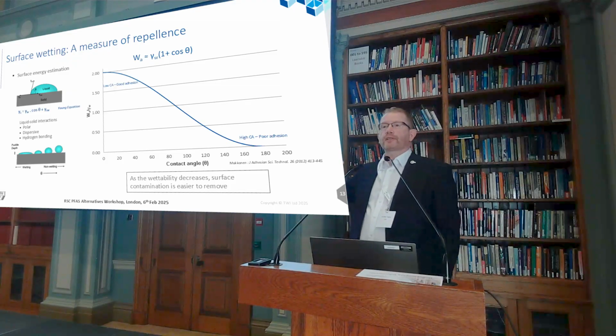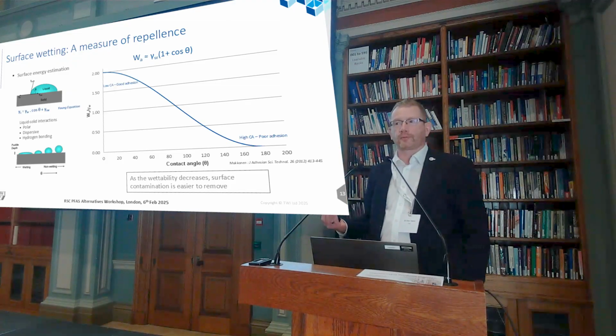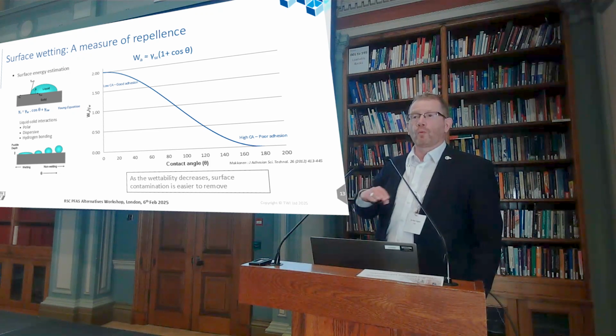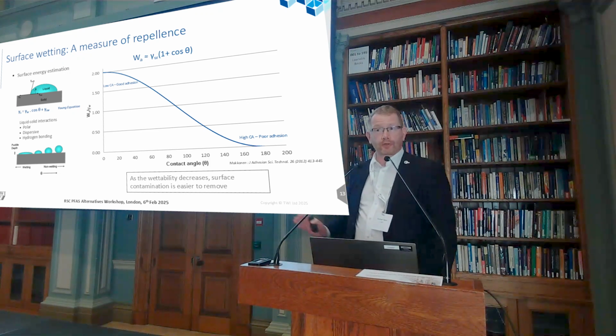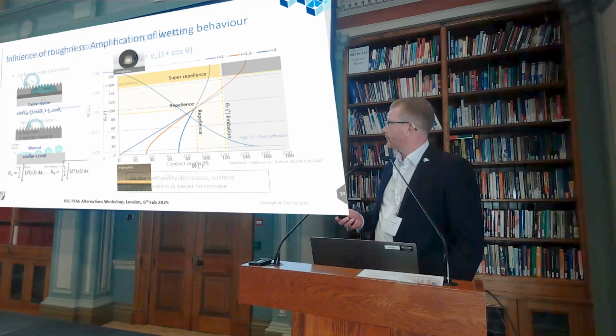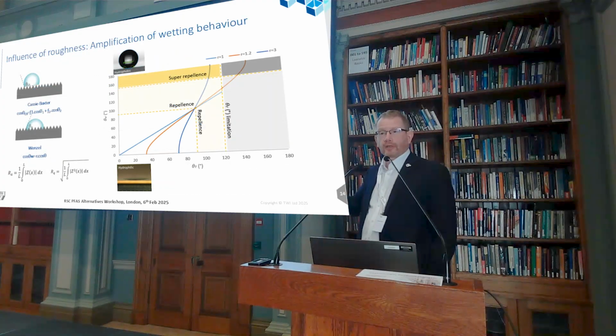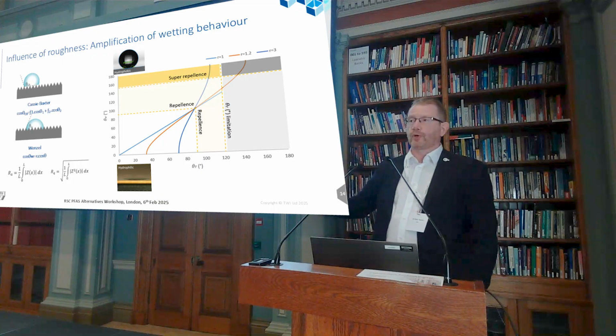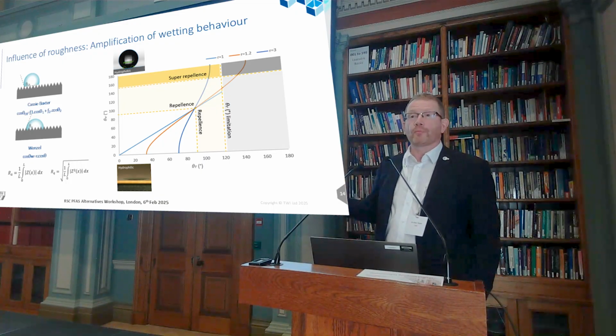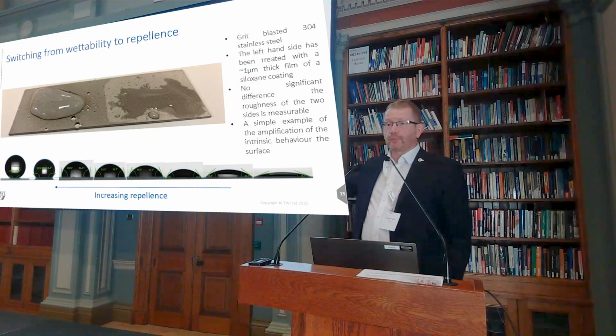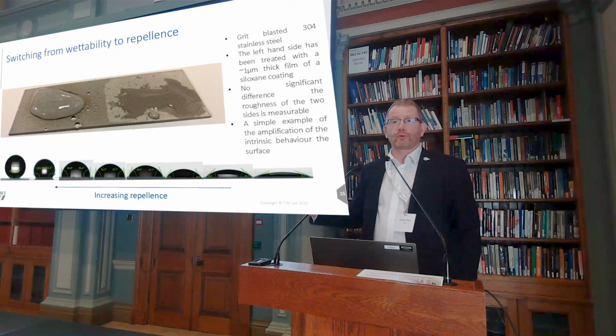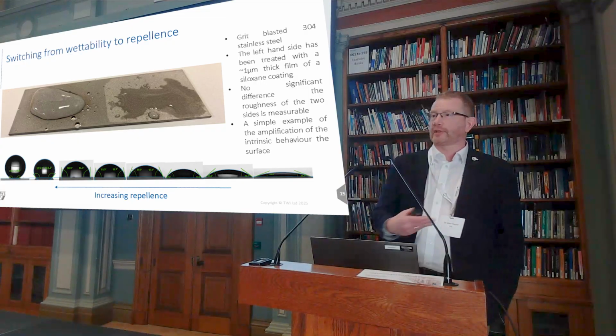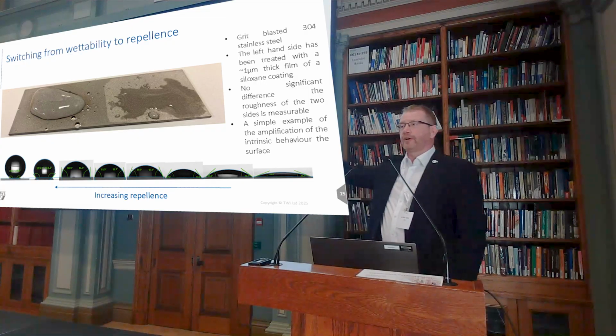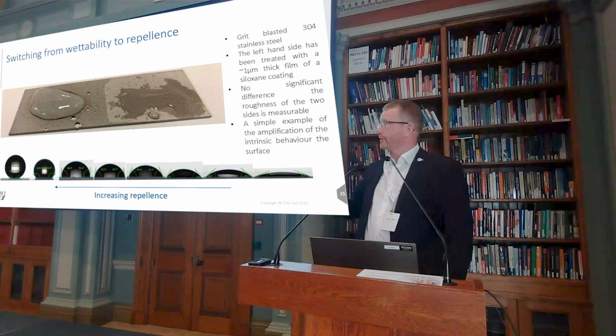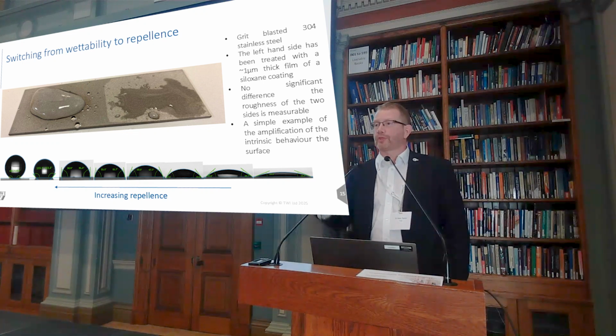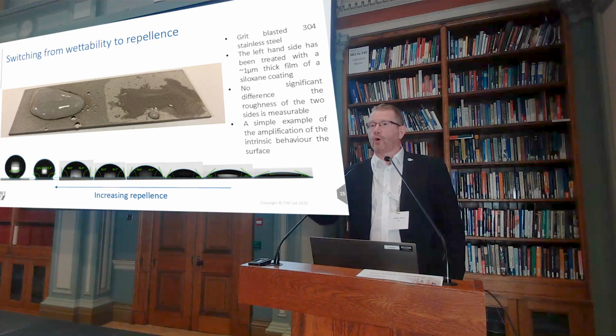So, quick graphs in terms of contact angle, because people always bring that up when you're talking in terms of hydrophobicity. Fluoropolymers, when there's no structure, tap out at about 120 degrees. If you want a higher contact angle than that, you've got to build in some roughness. And again, we've done quite a lot of work on the relationship between topography and chemistry in order to manipulate behaviours and repellence. There's an example here, a piece of stainless steel, which was grit blasted and coated with a very thin siloxane coating. On the left-hand side, super hydrophobic. On the right-hand side, super hydrophilic because of the roughness. Management of material properties and behaviours comes down to an understanding of all of those key factors.